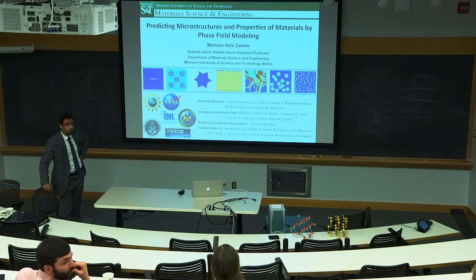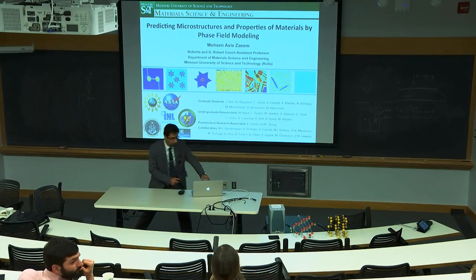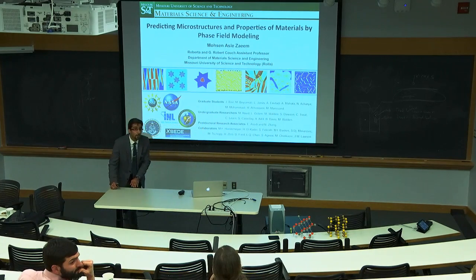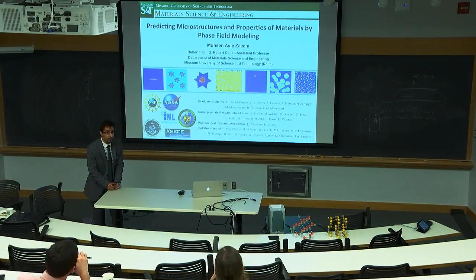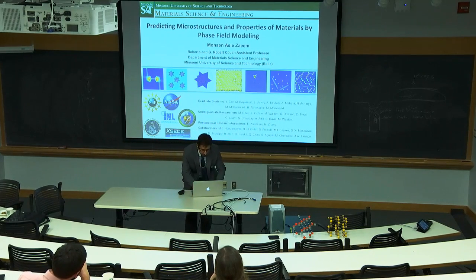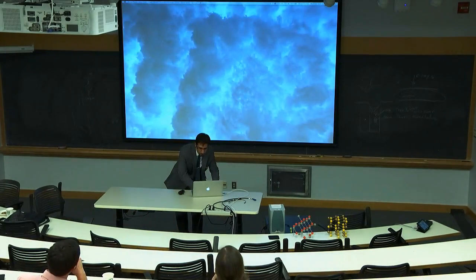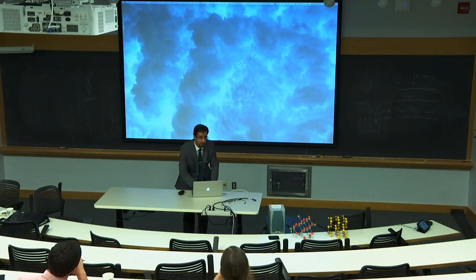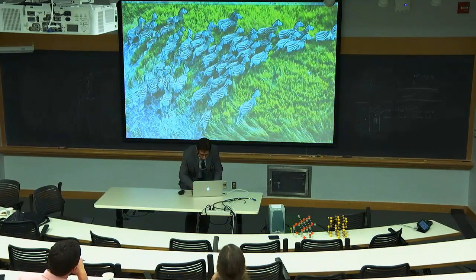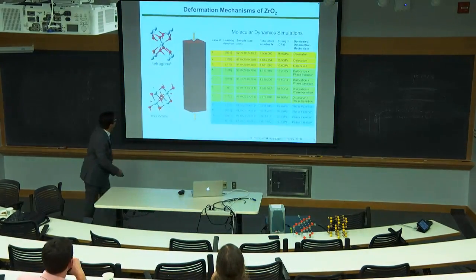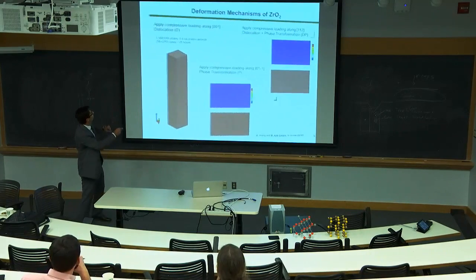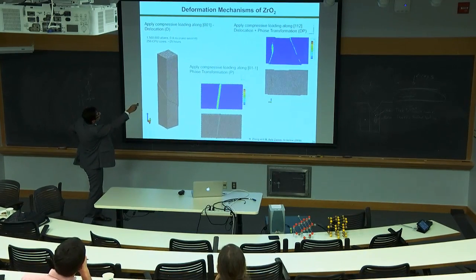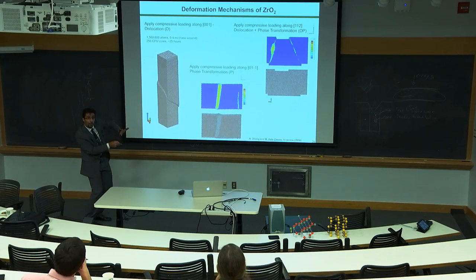You loaded it and you got a slip plane activated, and presumably that's some nucleation and propagation. Yes. Well, why didn't it fracture? We have cases that fractured. I don't have the fracture case here. That is the direction dependency. In some directions, you're going to activate the slip plane. If I go back to that example, here, if you look at this, the loading direction is 0, 0, 1. If we change the loading direction, it will change.